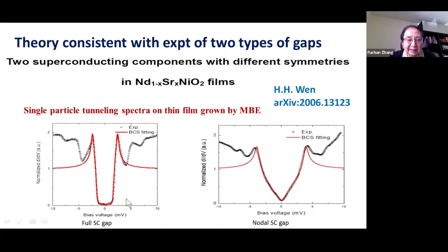Okay, and this is in the same sample in different locations, which may represent different doping in this sample, okay, which is quite common in strongly correlated systems due to the inhomogeneity. Okay. So at least we should be cautious to say that the experiment confirms our theory, but we can say that the theory is consistent with the experiment because of the 2 types of gaps. Okay.